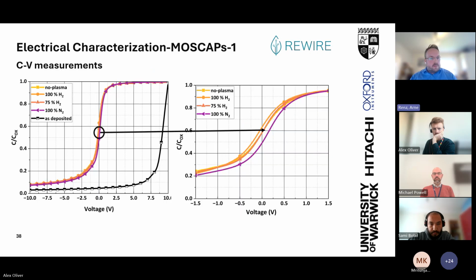And we can see here that when you look at key performance metrics, like the graph on the left, I'll keep it very light, it basically shows you the capacitance of the device plotted over voltage. You see the black graph here, which is basically an as-deposited ALD SiO2 oxide, which is leaky, it's not great. You see on the x-axis, it's not where we want it to be, which is quite close to zero, but by pre-tuning the material before we put down the oxide, we can bring it down to a very competitive state. The next slide, please.